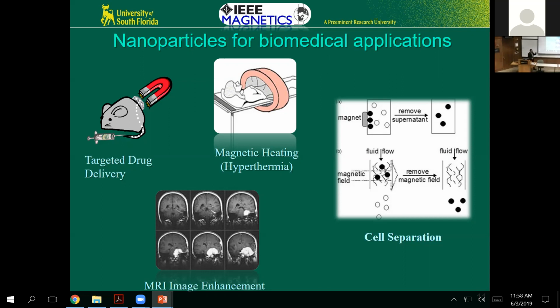Now, if you take magnetic nanoparticles and put it into the same area, the tissue, where you're doing the MRI scans, turns out that the fringing fields from these nanoparticles interfere with the relaxation process. So it basically decreases T2, it speeds up the relaxation. And from this, one can have an enhanced contrast of MRI images. So this is a very well-established area, lots of groups, lots of nice results coming out of this. So it's known that magnetic nanoparticles can be useful for improving the MRI contrast in these images.